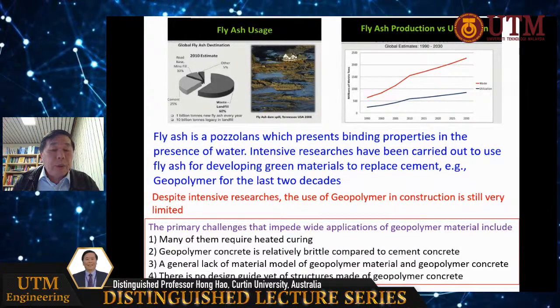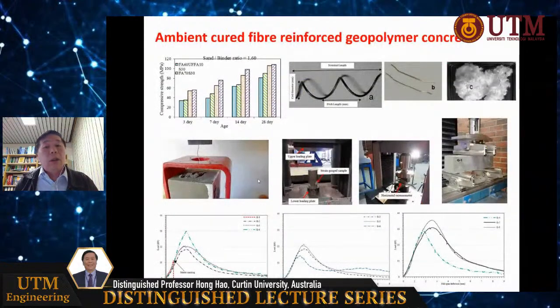They work on the material properties, but they do not develop the design guides or quantify the mechanical properties. So those are some reasons for its limited application. So we tried to do some improvement, and we developed, one of my PhD students from Pakistan, Musa Han, he finished last year, we developed ambient cured geopolymer concrete. That means we do not need heat curing, and we can reach a compressive strength of about 90 MPa.